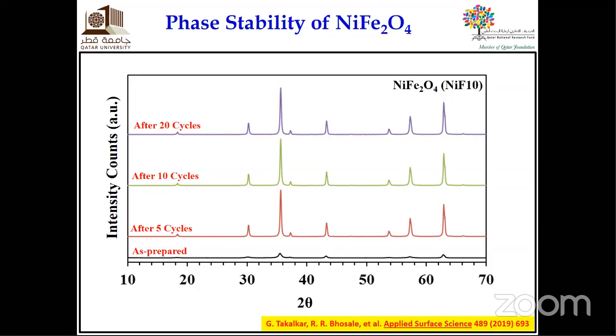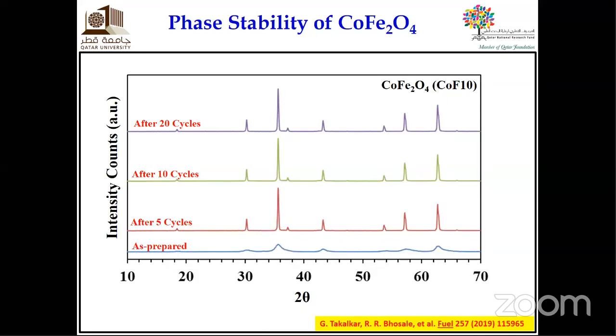We also did the XRD analysis to confirm. And this indicates that the nickel ferrite crystal structure remains intact. It doesn't go into any other crystal structure, or it's not broken like nickel and iron oxide. So we can say that whatever amount of fuel we have seen in the previous slide is because of the NiFe2O4 crystal structure. Similar thing was recorded in case of cobalt ferrite. It also remains quite stable. And we can claim that whatever fuel production we have seen is because of the CoFe2O4.